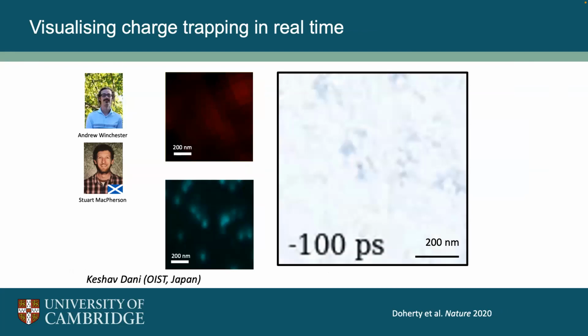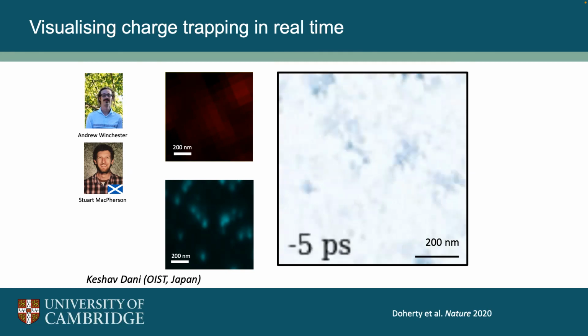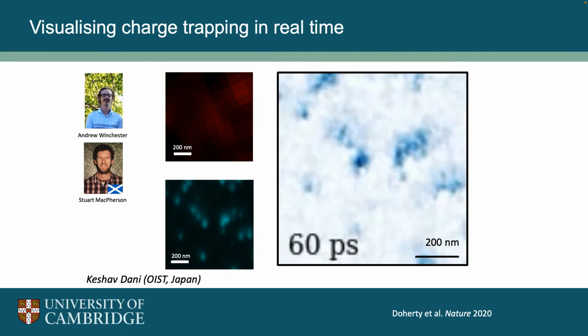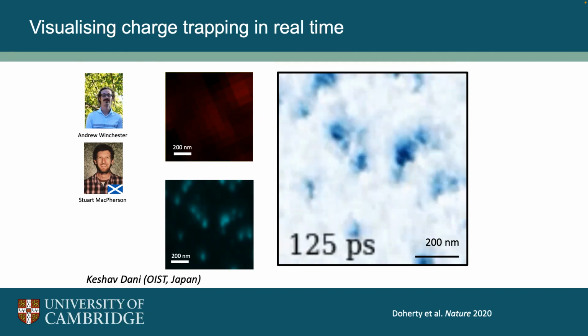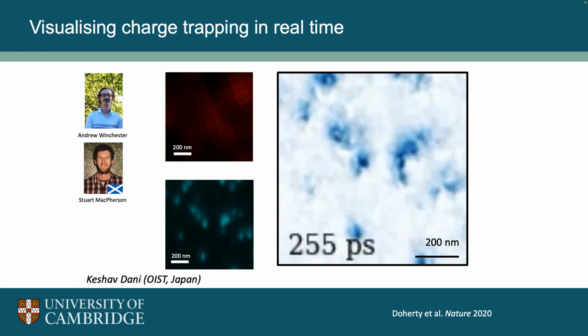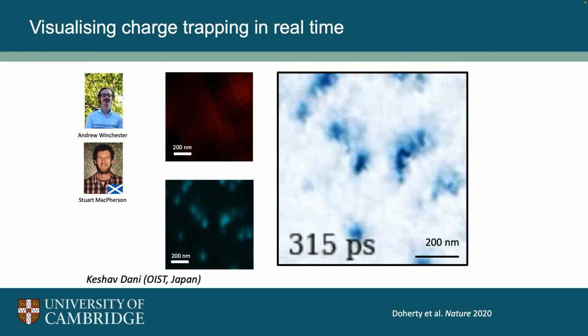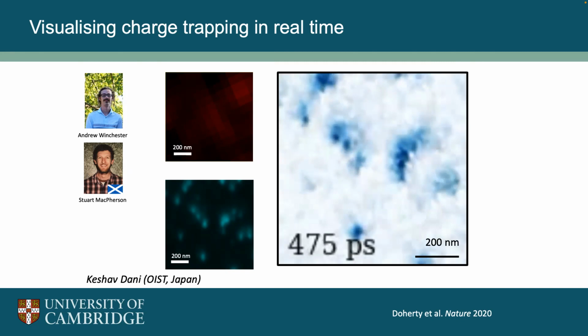We can also actually visualize this trapping process. This is a technique where it's essentially a photoemission technique in an electron microscope, and we excite with a very fast pulse of light. And what I'm going to show here is when we get to 0 picoseconds, that's when the light comes, you're going to see carriers trapping in these tiny trap clusters. So these dark regions here are where these energized carriers are trapping. The technique is fantastic. We can really start to see now on very, very small length scales and very fast time scales these carriers trapping, and this is essentially leading to a loss in the solar cell. It's something we need to get rid of.